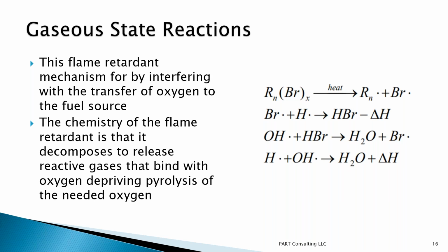Gaseous state reactions, there's a lot of chemistry, but basically the components of the flame retardant break down, and in this case you're seeing bromine. Bromine in turn reacts, forming HBr, and that process absorbs an awful lot of heat. The HBr also reacts with other elements in the fire, and basically it starves the substrate or the fuel of oxygen needed to continue the burning state.